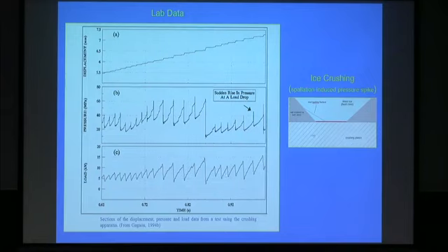Interestingly, when that spall shatters, the load then transfers to the remaining hard ice. And that is the source of the spike in the pressure that Kai referred to before. There are some really important things that happen during that spike. That spike happens on the scale of 950 microseconds. So it's a very, very narrow event, but some important things happen in there.